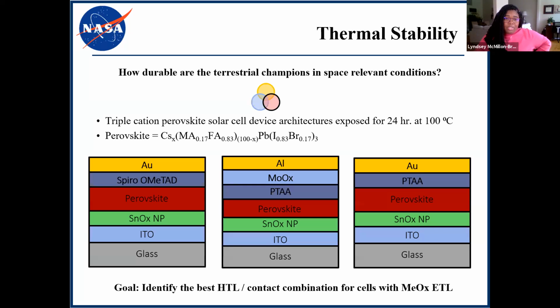So if you remember the optimization Venn diagram, we're really focused on durability in these studies. So we're looking at these architectures that were developed from previous work funded by the DOE, and we're varying the topmost layers here shown in these NIP device schematics. And we want to see what's the best hole transport layer contact combination for cells that have metal oxide electron transport layers. So in this case, our active layer is a triple cation perovskite whose device architecture is shown.